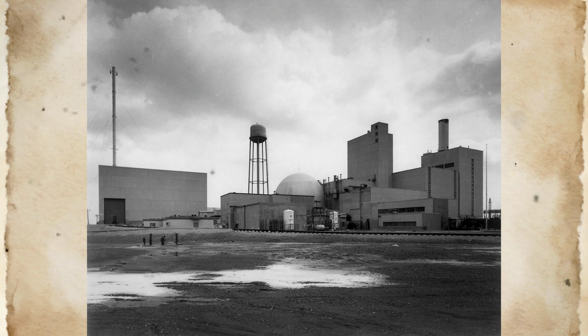The attachment methodology for the flow distribution plates employed welding techniques adequate for static structural loads, but potentially inadequate for the dynamic hydraulic forces present during reactor operation. The plates experienced temperature variations from ambient conditions during shutdown to approximately 300 degrees Celsius during operation, creating thermal stress cycles that could propagate fatigue cracks in weld joints over extended periods. Flow-induced vibration from sodium circulation added additional cyclic loading that compounded thermal fatigue effects. The failure to recognize these plates as safety-critical components created a gap in design rigor that would prove consequential.